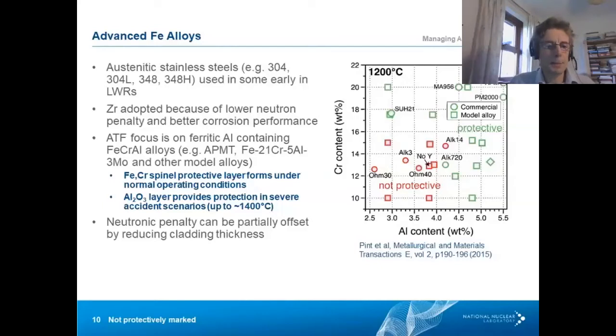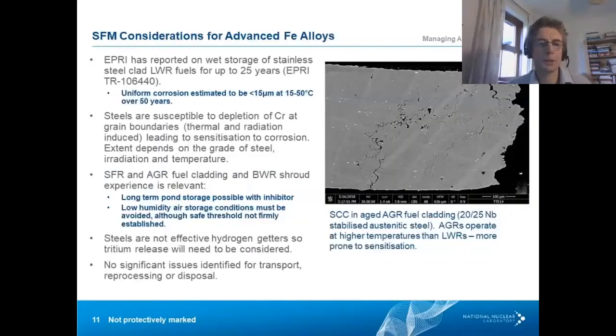In terms of the impact on the back end of this presence of steel clad, we know from experience that stainless steels corrode very slowly over very long periods of time. In some cases, or some combinations of temperature and neutron irradiation, depletion of chromium at grain boundaries can occur, and that can lead to sensitization. Although the extent depends on exactly the grade of steel and the irradiation conditions, storage conditions that mitigate the risk associated with corrosion have been established around the world.